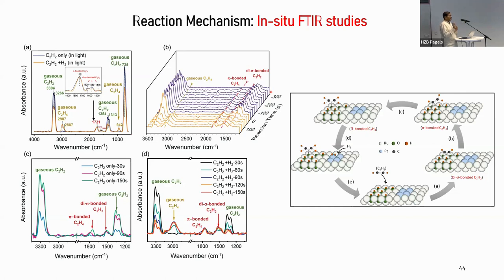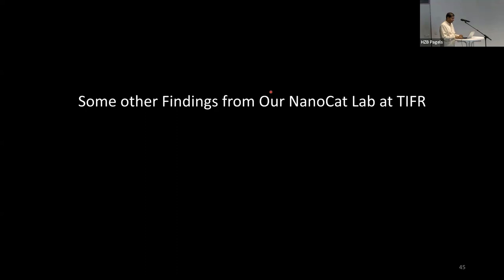And since Ru-Pt can only do the hydrogen dissociation, not the acetylene activation, activity goes down. As soon as I put in the air, some of that Ru goes back and oxidizes into RuO2, which is the active site for acetylene activation. And then Ru-Pt, there are still some Ru-Pt which will dissociate the hydrogen and the reaction happens. So that's what we try to understand by the in situ FTIR studies and lots of XAS studies.